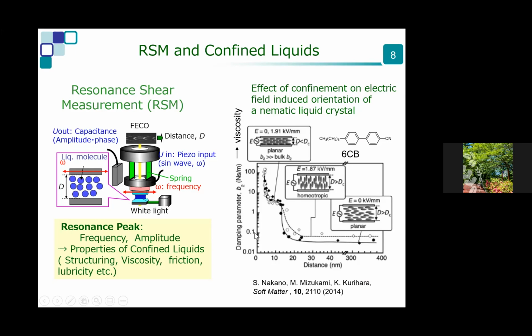There are many interesting phenomena we could observe using such a device. The right-hand side figure shows examples. We confined liquid crystal molecules between a gap and studied their viscosity using some models. This damping parameter corresponds to the viscosity, and at distances below 20 nanometers, viscosity started to increase like this.